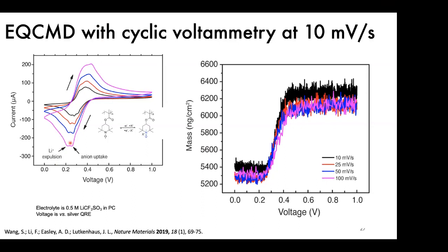Would this be affected by the kinetics of the ion diffusion? Because if your ion diffusion does not match up with your electron transfer, then you definitely will get something like more polarization, which you can see from the lithium one, which goes to lower potential when you reduce it back, right? Right, I think that's a possibility. And then we also need to consider that even your electrode will have some electrolyte penetration in it, even with carbon in it. There's still some reservoir of salt in the electrode. So that may get consumed, and then that may allow anions from the bulk to come in.